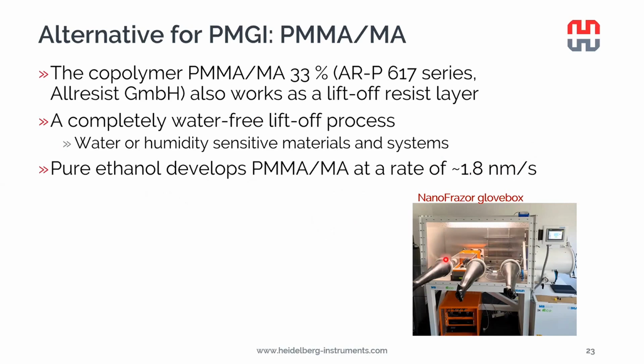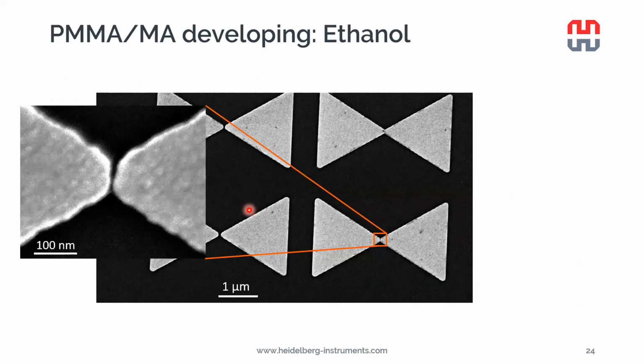So in the glove box environment, one can carry out the entire sample spin coating and patterning, then developing, and the metallization and lift-off process completely in a water-free process. Interestingly enough, I also managed to achieve the smallest ever nano gap between metal electrodes using ethanol developing and PMMA MA. It might be a coincidence, or it might be a property of the material, I don't know. But anyway, this is done using the freestanding PPA bridge process that I showed before.